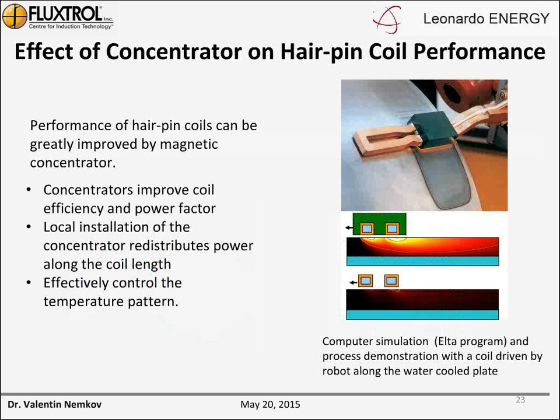Here, let's start with the effect of concentrators on hairpin coil performance. The hairpin coils may be greatly improved by magnetic concentrators. Concentrators improve coil efficiency and power factor. Local installation of the concentrator redistributes power along the coil length, and therefore effectively controls the temperature pattern in the part. On the right side, you have the picture of the installation, which became actually classic in demonstration of the effect of concentrators.